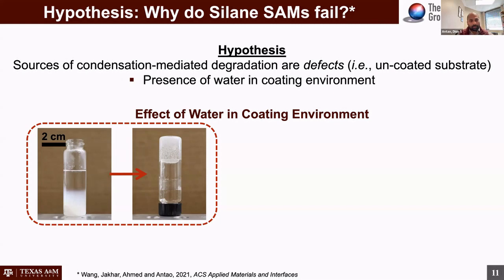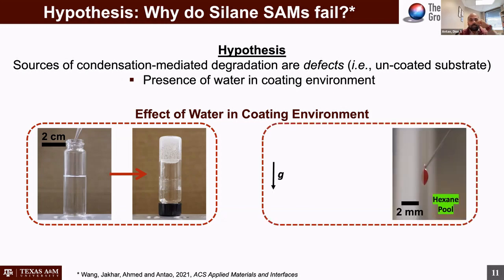And so, in essence, this is happening at the nanoscale also on your substrate, which is preventing you from having monolayers, and you tend to have potentially multi-layer coatings. The other aspect is if water is present in the coating environment, the question is, does water have a higher affinity for the substrate than your solvent, which contains your silane molecules? And if water has a higher affinity for the substrate, water is likely to mask the substrate from the solvent, and hence you will again have defect sites where there's no silane bonded to the surface.